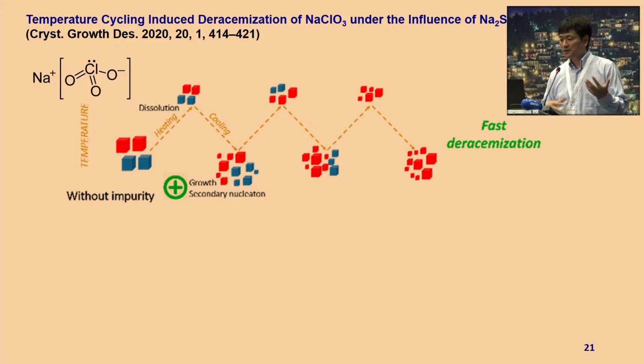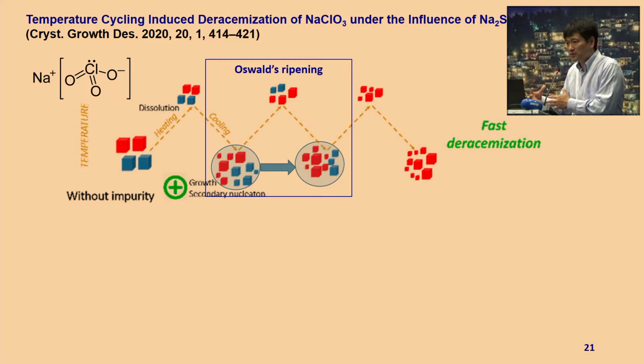Another example is if you have a mixture of two enantiomers in solution, the way to separate is that you have crystals in there and you use temperature cycles, heating and cooling. In the process, because you have two solids, R and S, they have somewhat different dissolution kinetics. During the first step of dissolution, one enantiomer forms smaller crystals. They will dissolve, and when you cool it, one enantiomer becomes smaller, and then when you heat it again and cool it again, these smaller particles dissolve faster. This is based on Ostwald ripening, the same idea. So the one which is smaller becomes less and even smaller. Eventually, you can get the pure enantiomer.